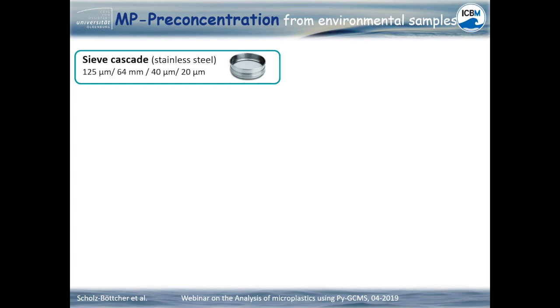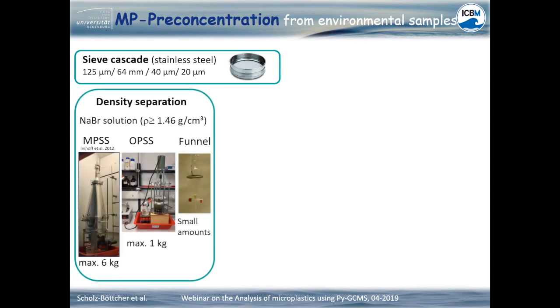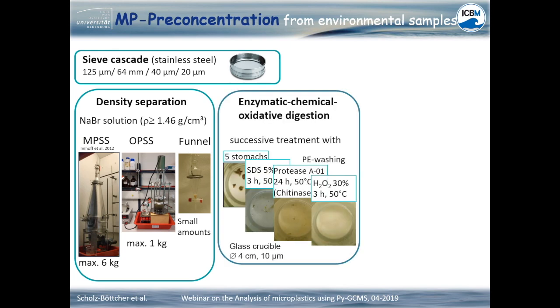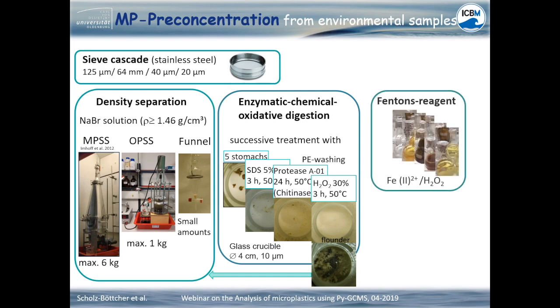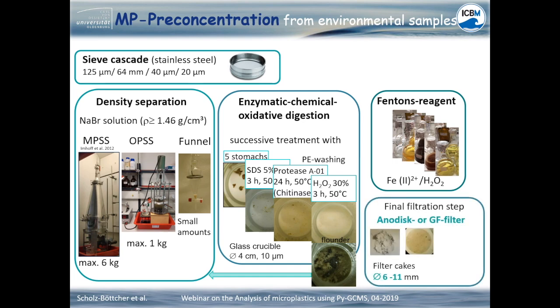Sample-dependent, we use a combination of different methods for microplastic extraction from environmental samples, such as sieving cascades, for example for water samples, density separation with high-density sodium bromide solution for sediments, enzymatic chemical oxidative digestion for biota samples and, sample-dependent for others, oxidation with Fenton reagent, and in some cases a combination of all.